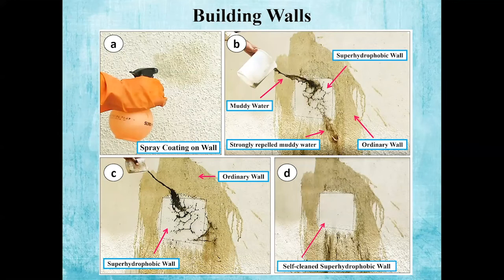Building walls. Yes, we take care of internal building walls, but we are not so interested in the outer building walls. We clean them very lazily. But we have coated a building wall, not all of it, but you can see in picture B the square part. That square part is coated with the superhydrophobic coating, PMMA and silicon nanoparticle. Even if you put muddy water on it, the square part is not getting dirty. However, outside this square part, which is not coated, it easily catches the muddy water and eventually gets dirty. So a self-cleaning superhydrophobic wall can be dreamed of in the future too.